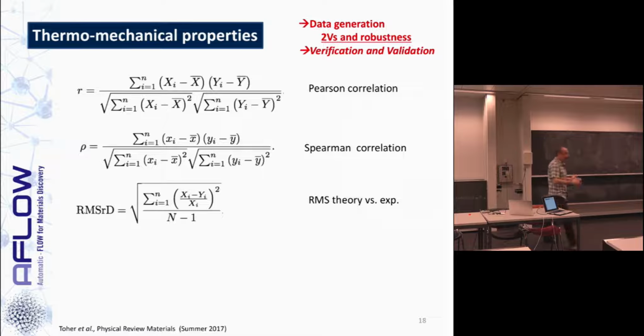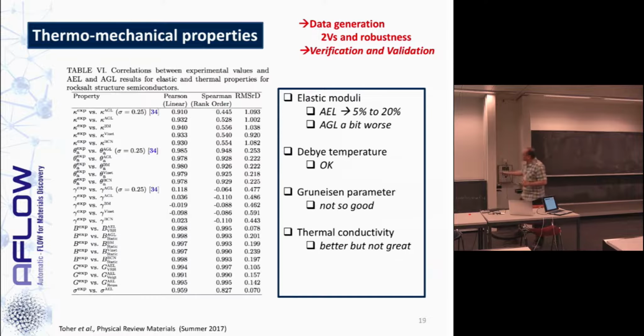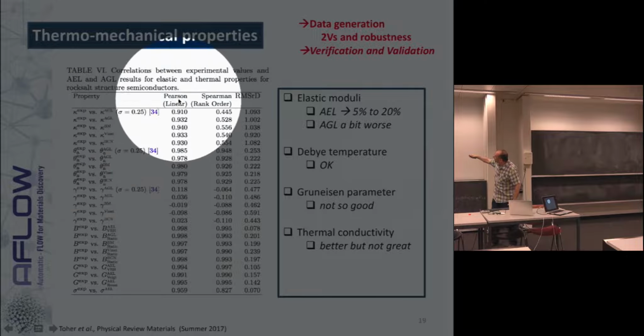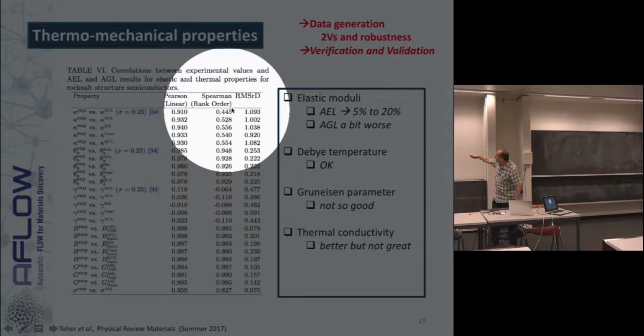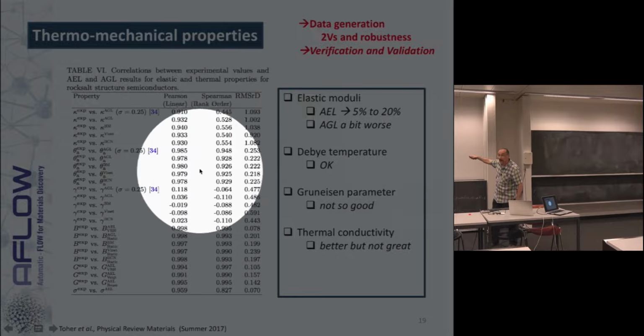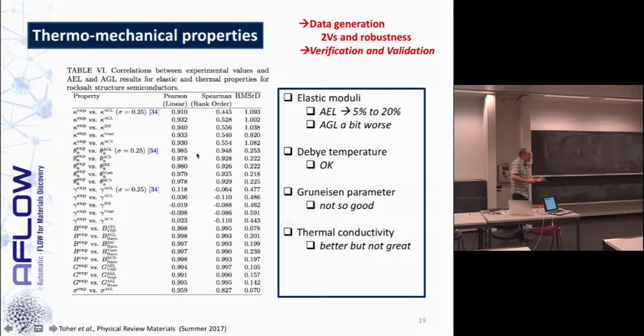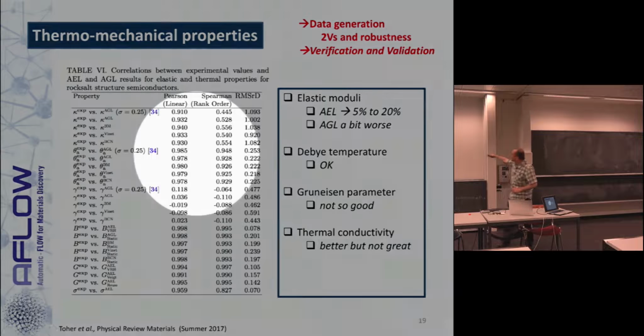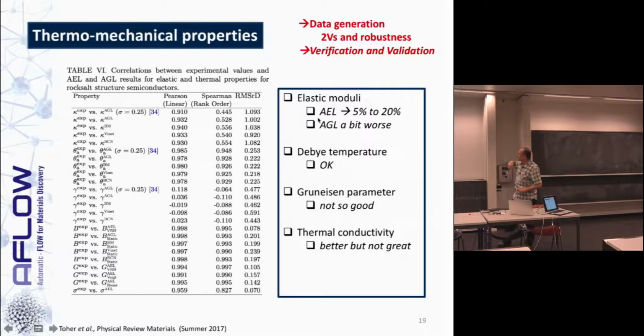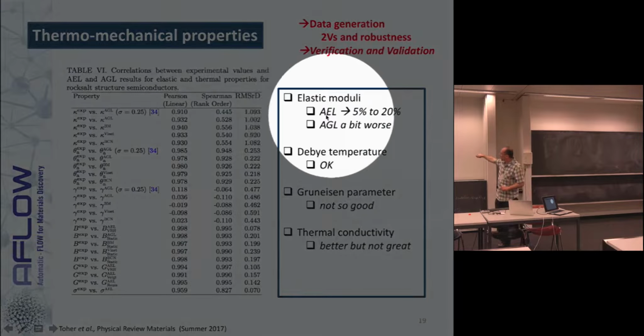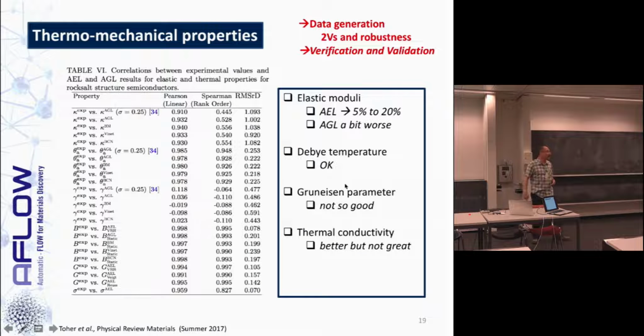And for instance, in certain cases, like the thermal conductivity, we could spot that regardless of the fact that the thermal conductivity is not too off from the experimental data, this is the standard correlation, it is very off from the Spearman analysis. So that means that we could not trust any prediction on the thermal conductivity done with that model. And quantitatively, we have a very good prediction of the elastic moduli. The Debye temperature is sort of okay, but Gruneisen and thermal conductivity need to be improved.